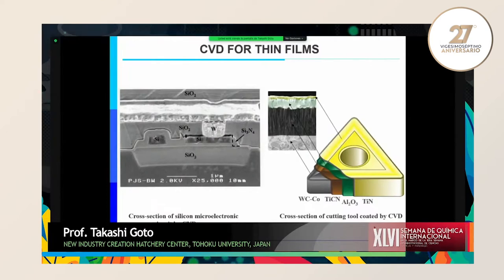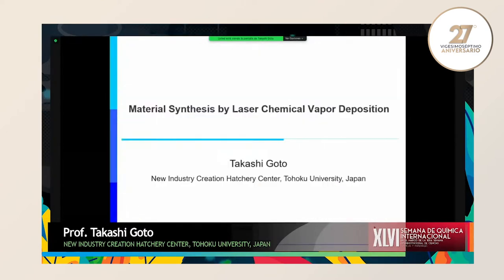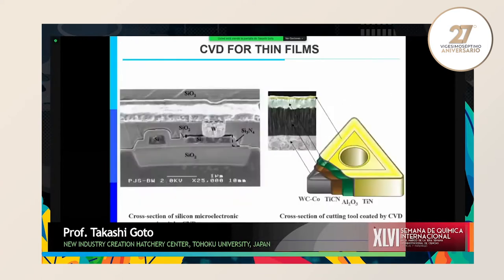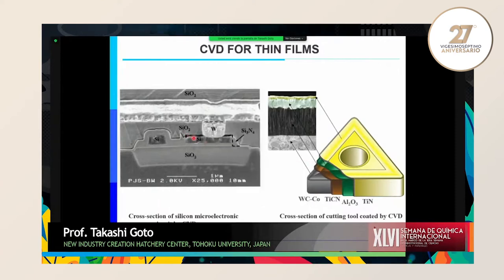These days, many components like silicon, silicon oxide, silicon nitride, and tungsten are all prepared by CVD. Tungsten carbide cutting tools, for example, are coated by titanium carbonitride, titanium nitride, and aluminum oxide by using CVD.